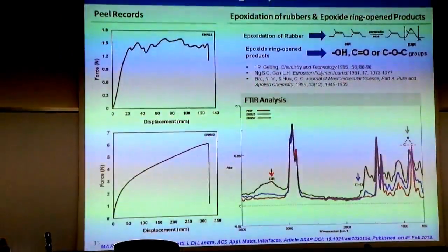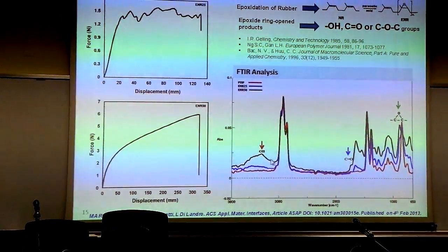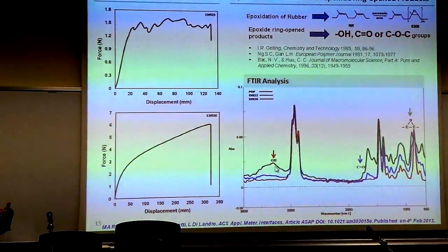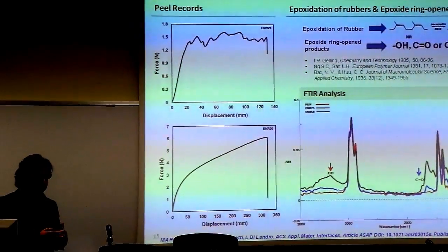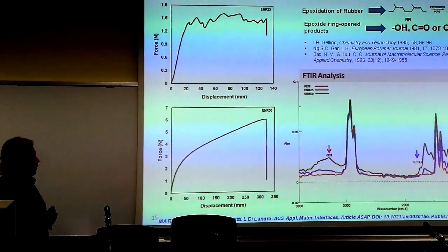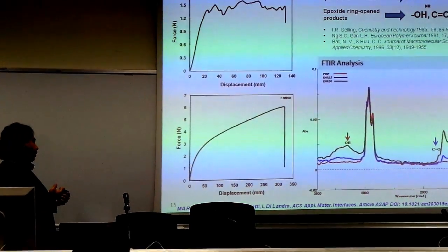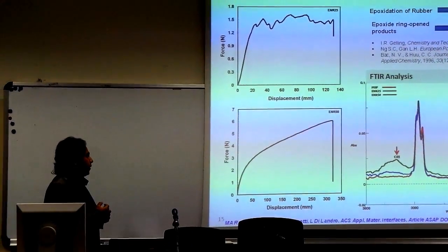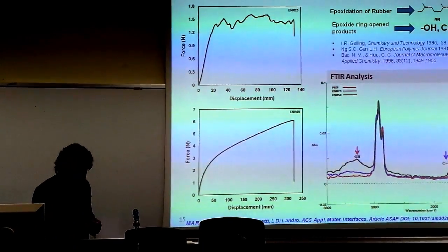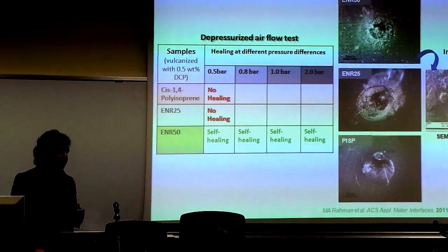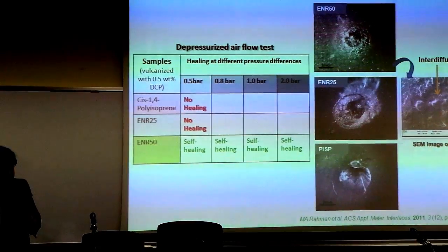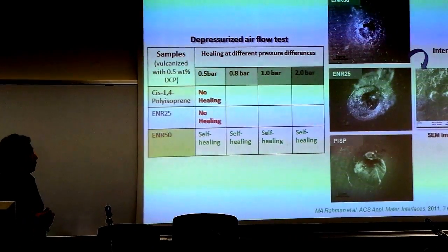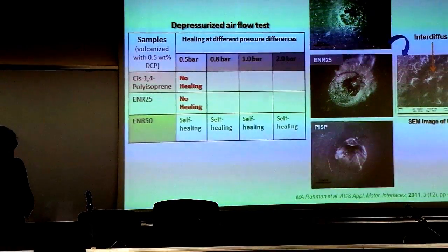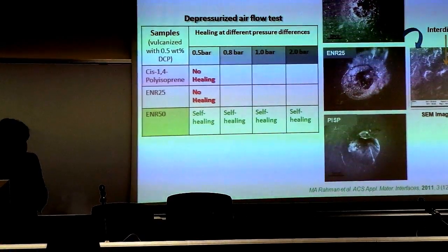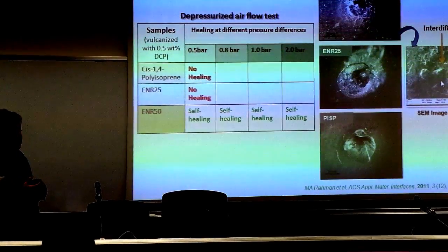And in the FTIR analysis of my sample, I found that the FTIR spectra of ENR 50 shows the presence of some polar groups like hydroxyl group, carboxyl group, ether groups, and also the epoxy group. And this gives further indication about the importance of having higher mole percent epoxidation and also the presence of polar groups that can lead to the higher peel strength in the ENR 50. I also studied their self-healing behavior in ballistic test condition, and in the ballistic test condition, I found that only ENR 50 having 50 mole percent epoxidation level showed complete self-healing behavior. And if you take a closer look at the impact zone of ENR 50, it shows a complete interdiffusion at the impact zone.